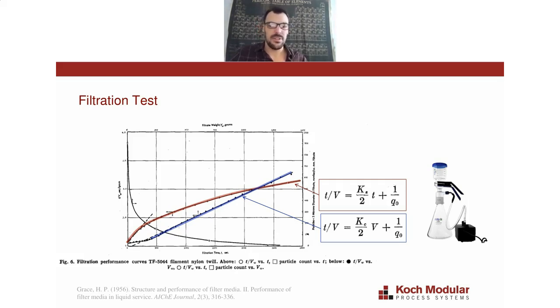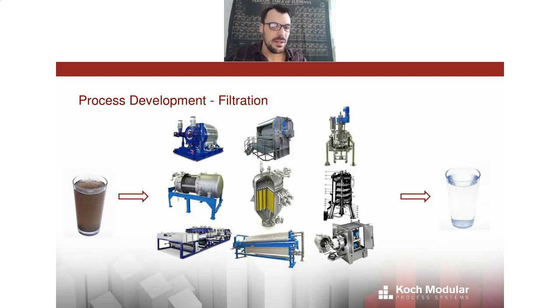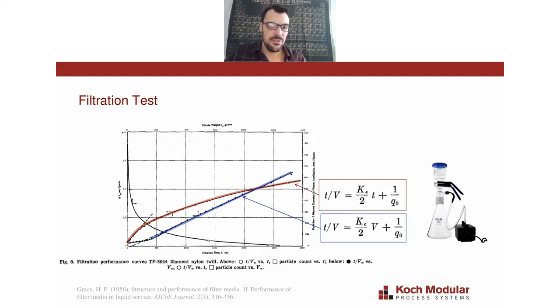So this can guide you in the selection of a filter. Some of these filters are amenable to having very thin cakes and are better choices for standard blocking, the T over V versus T, the red curve. You're probably going to be designing for a thin cake filter. The blue curve, T over V versus V linearization, does enable you to generally choose a thicker cake filter. The red curve is going to be more amenable to filter aid. That's the cases where I would recommend trying filter aid to get some structure in that cake to prevent the pores from collapsing. The blue curve, probably less of a benefit for filter aid.